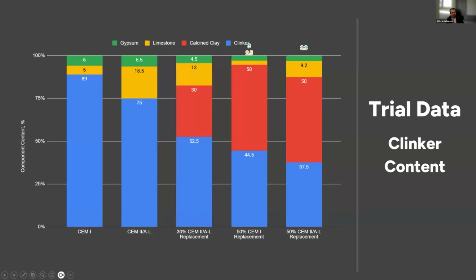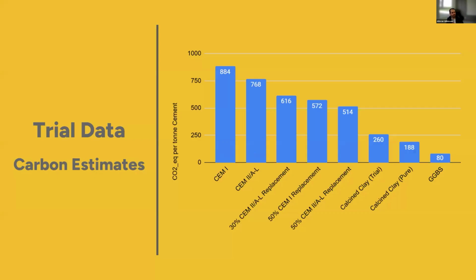Okay, the most important aspect for us now alongside the performance is really where the carbon and the clinker contents come in. So we're seeing a drop off in clinker. We've been able to achieve as low as 37% and still get pretty good results. But for us, it's the 50% or the 44.5% clinker, the 52.5% clinker that makes massive differences on your embodied CO2. So CEM1 for us is about 880, and with your CEM1 replacement, you're dropping that from 880 down to 570, and a high replacement of CEM2 down to 500 kilos of CO2 per ton.